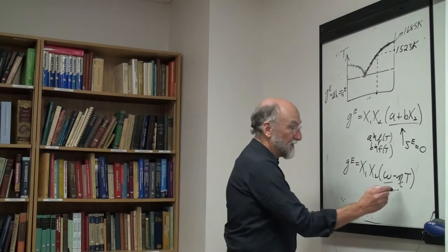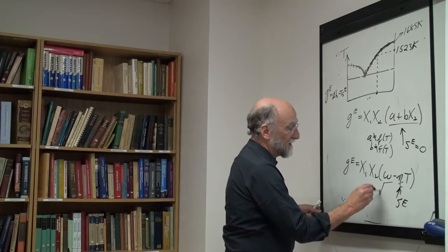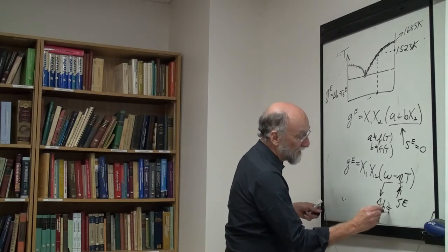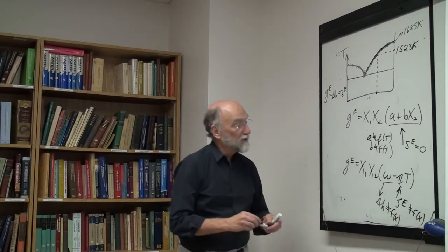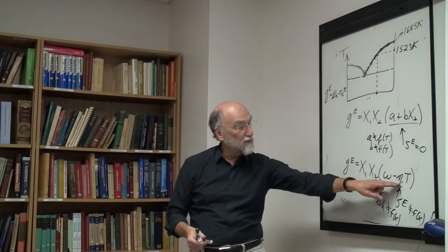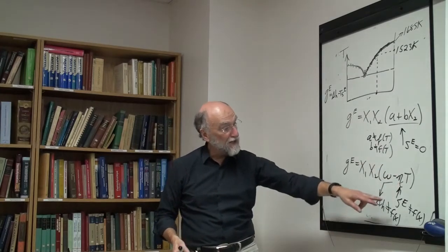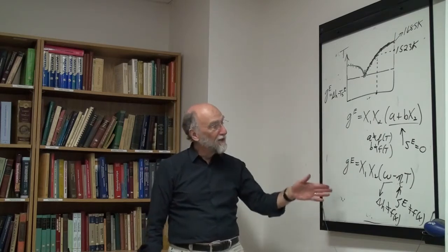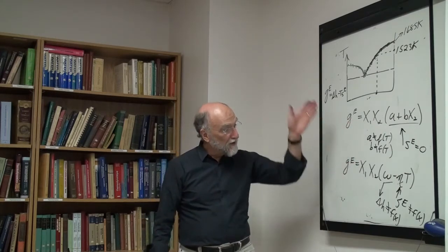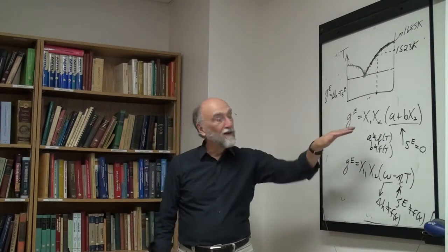In this case, this is SXS and this is delta H. It's not a function of composition, and this is not a function of composition. So here I'm assuming a constant H and SXS independent of composition, but SXS is not 0. So GXS varies with T, but not with composition. GXS over x1, x2 varies with T, but not this way.